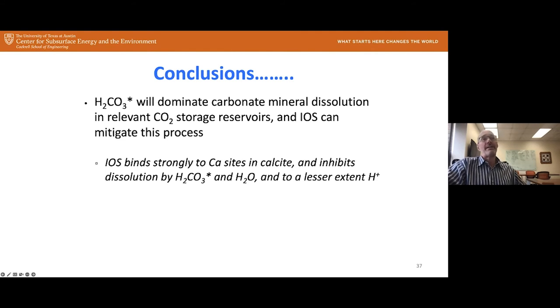And the last one is that this carbonic acid is going to dominate carbonate mineral dissolution, which would be expected in these, let's say, carbonate cemented CO2 storage reservoirs. And we observed that IOS can mitigate this process. Through different types of analysis, we found that this IOS binds strongly to these calcium sites, and this inhibits dissolution by this carbonic acid in water, and to a lesser extent, protons.